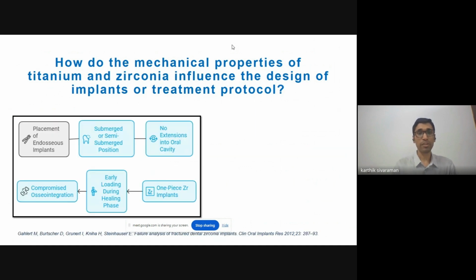What else? Now, when we place an implant, we prefer that we place it in a position whereby there is no early loading of the implant during the healing phase, because it can impair osseointegration or the bone implant contact. However, when we place a one-piece zirconia implant, there is a greater probability of early loading during the healing phase and compromise osseointegration.